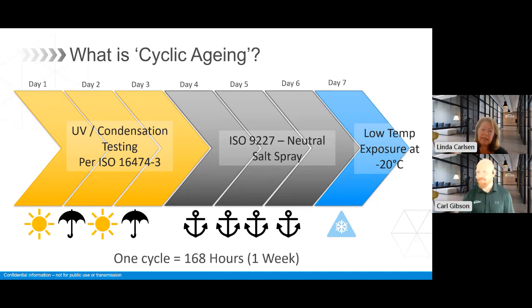Excellent. This freezing is actually the one that makes the difference and stresses the system extra. And it's the difference that they might want in the new revision because it's more according to the normal environment. Yeah, what we see. And we also see that a lot in the testing that we have done. If we're comparing with and without the freeze cycle, it's quite a big difference in the results.